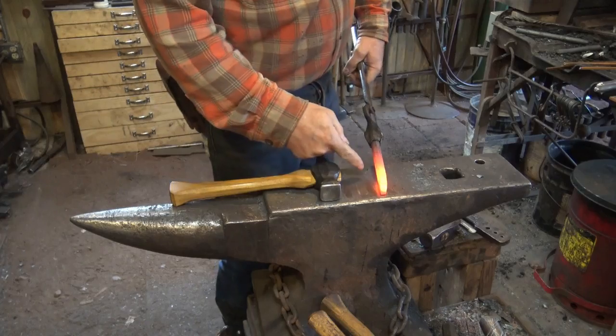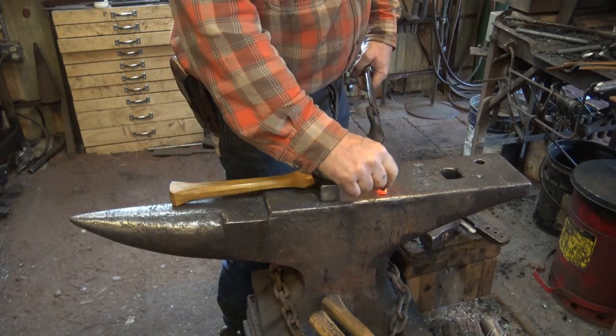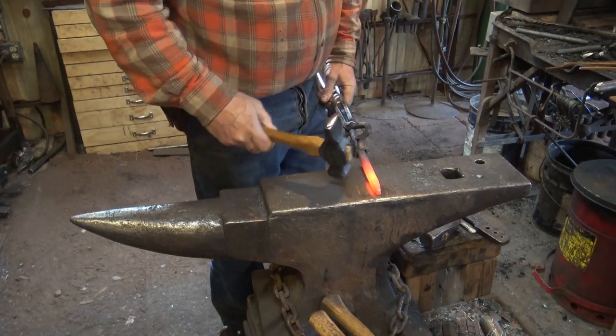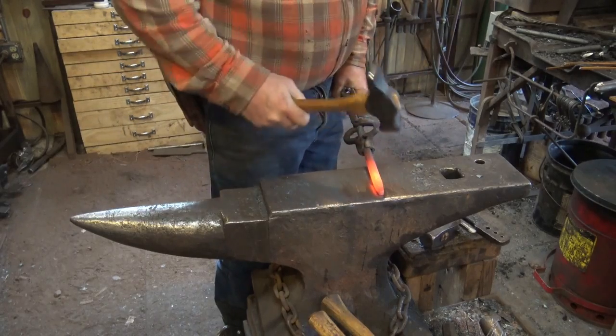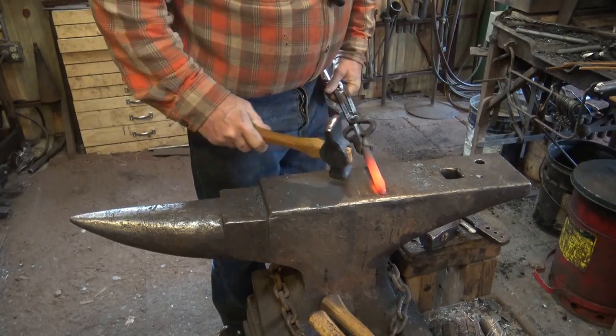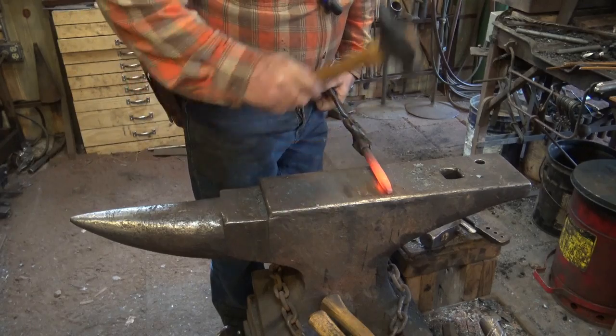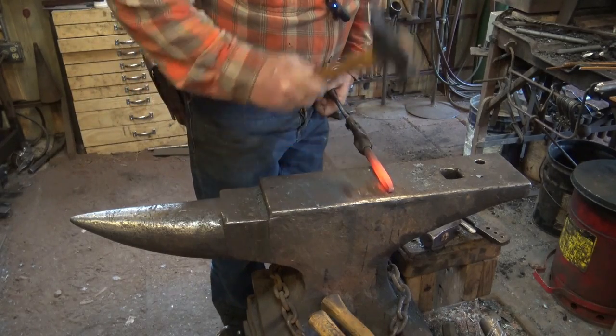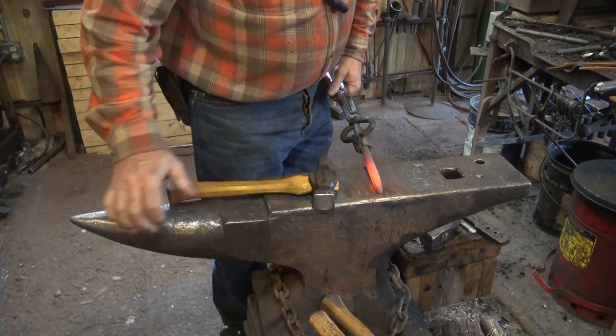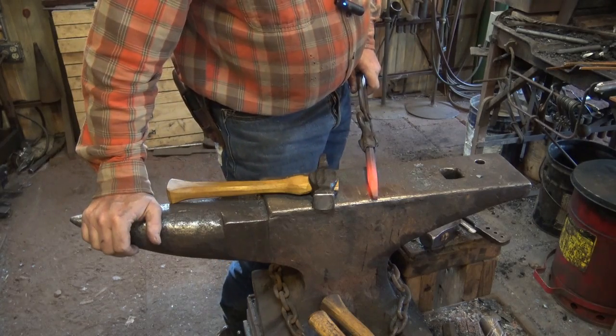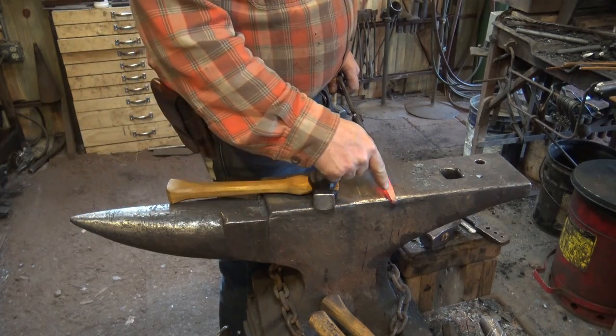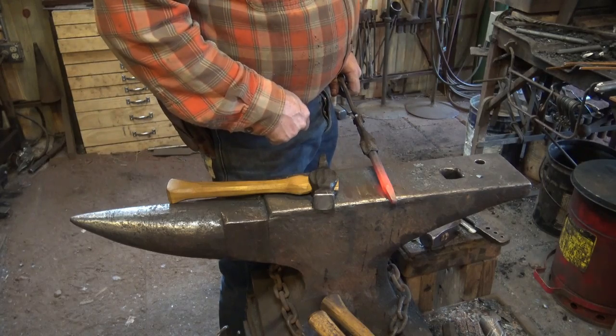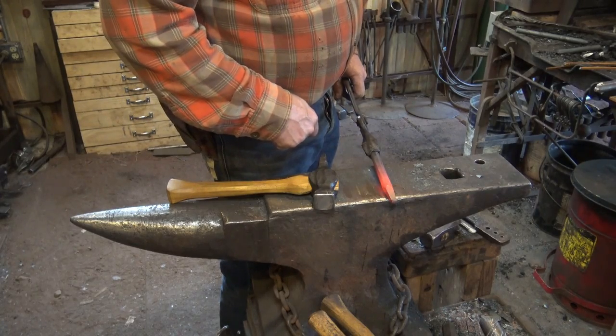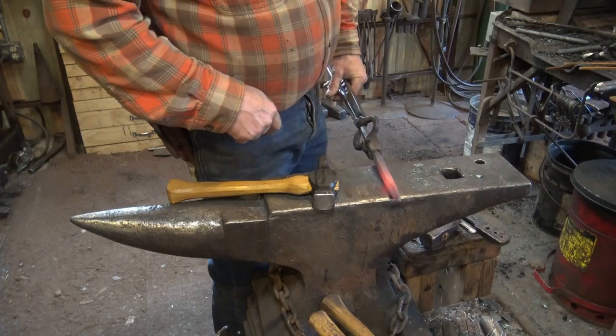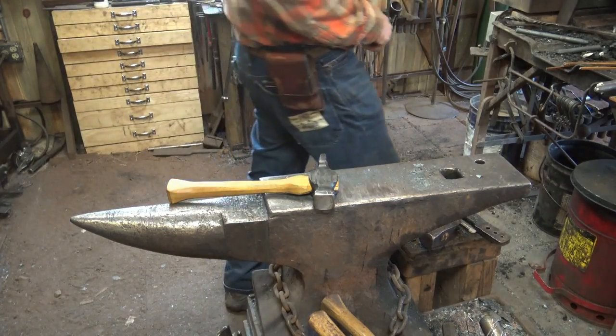Now you don't want a shoulder way up here with a 1/4 inch parallel. You'll end up bending that punching material. Most of what you're punching will only be about 1/4, 3/8 thick, half at the most. So as long as you've got about 3/4 of an inch of decent round punch at the end, it's going to be plenty to punch a good hole.